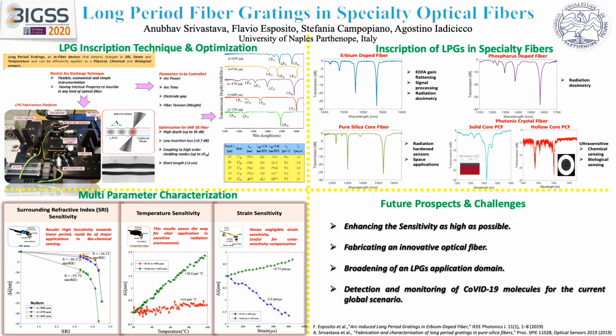So we can see here the operating principle behind the electrical arc discharge technique. We can see in the figure that it involves a stripped section of an optical fiber positioned between the two electrodes. During the entire process, one end of the fiber is firmly fixed on a remotely controlled precision translation stage, while the other end is kept under constant axial tension, ensuring the straightness of the fiber between the electrodes to maintain an even power distribution on the whole length of the fiber.